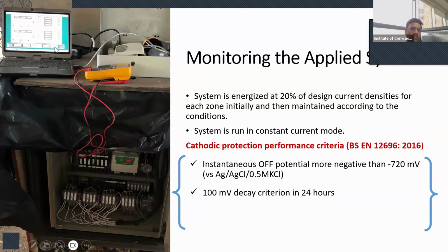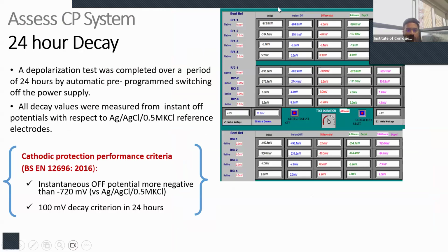This is the communication box, and through this, from the laptop, we can set the amount of current we need to pass. We can monitor 4-hour decay, 24-hour decay potential values, the on potential values. The system was initially energized at 20% of the design current density and then monitored according to the baseline. This is how the typical window of this communication board system looks.